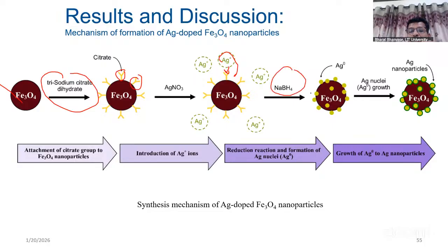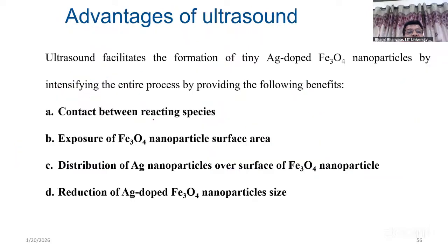With the addition of, you can say, the presence of sodium borohydride, there is a formation of nanoparticles in this. So suppose we can say Ag dope Fe3O4, then it's nuclei, then after growth, this complete Ag is deposited on Fe3O4. This is the mechanism what we have proposed.